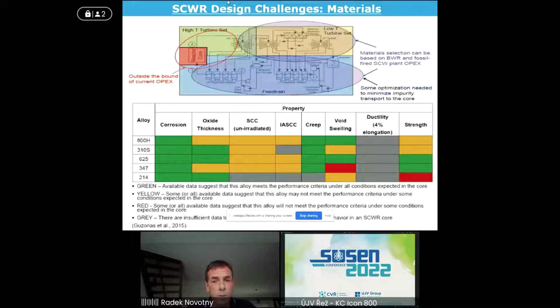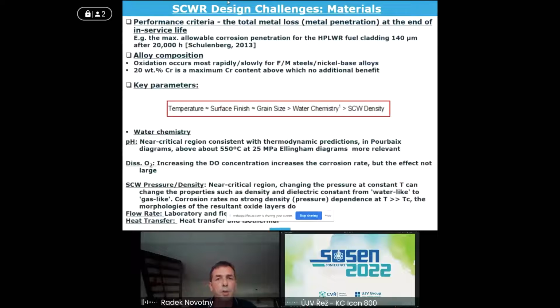In reality, we don't have any alloy at the moment which would fulfill all these criteria, and we have real gaps like in stress corrosion cracking testing, irradiation assisted stress corrosion cracking, and so on. I will comment later on this. If you look at the design criteria, one of the things defined in the HPLWR phase 2 project was the performance criteria, which was defined as the total metal loss at the end of service life, and it was defined as 140 micrometers after 20,000 hours of service life.